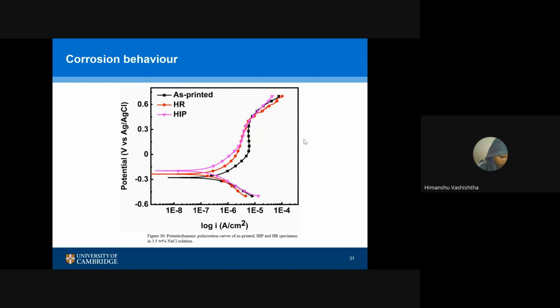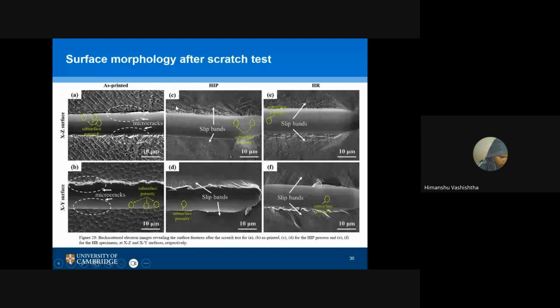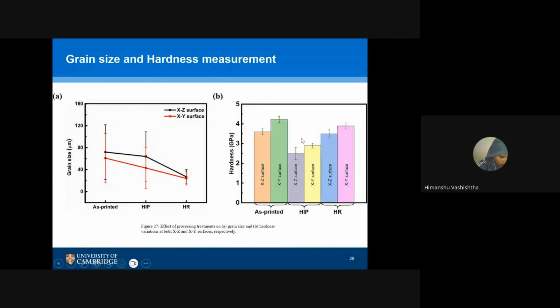We have investigated the corrosion behavior for the complete replacement. You can completely recommend any product only when you have all the calculated properties from the microstructural point of view, mechanical point of view, and corrosion point of view. For the as-printed case, we have the lowest corrosion resistance, and for the hot isostatic pressing, we have the highest. Earlier it was giving us pretty good mechanical properties, however, in terms of corrosion, it's reversing. Hot isostatic pressing is giving us pretty good corrosion resistance, even the highest among all three.